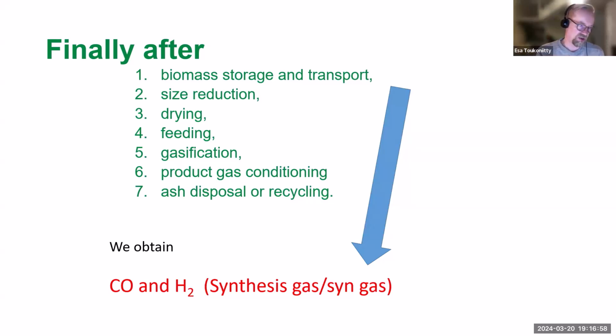The tar formation was one that was mentioned. Also, the ash formation is quite specific. I can imagine that it comes from the biomass, because fossil-based materials don't contain so many alkaline and alkaline earth minerals, and also not phosphorus and such, which is typical for biomaterial.